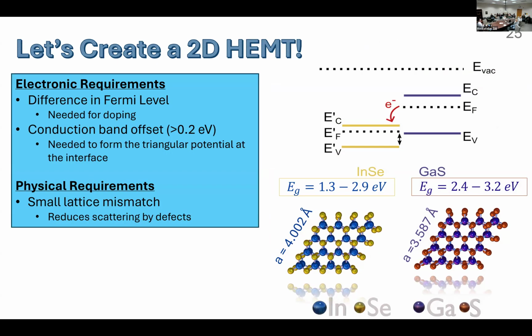So to see if we can create a 2D HEMT, we have to look at the electronic requirements and the physical requirements needed. The electronic requirements include a difference in the Fermi level. We need this to introduce doping. We also need a conduction band offset between the two semiconductors used. This is needed to form the triangular potential at the interface that will trap the electrons.